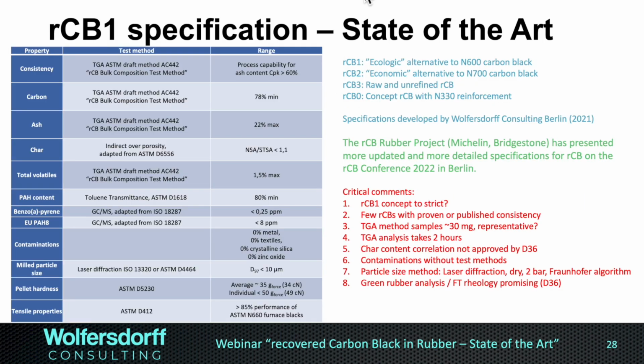I won't go through details of my specification. For me, it was important to define and also to quantify consistency. And I looked at the process capability with a CPK value. Of course, the downside is only very few RCB producers are industrial and have that data to actually prove that process capability to control the ash content to a CPK greater than 60%. That is actually based on true values I have from one manufacturer, but I think very few manufacturers are measuring the ash content or the inorganics content on a daily basis.